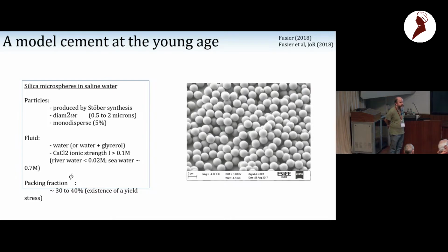Very nice talk, very nice work. Did you try to look under an electron microscope at samples that were aged for different times, in order to see whether you pick up something at the particle-particle contact level, like particles sintering, silica dissolved and redeposited? That's a very good question. We haven't.